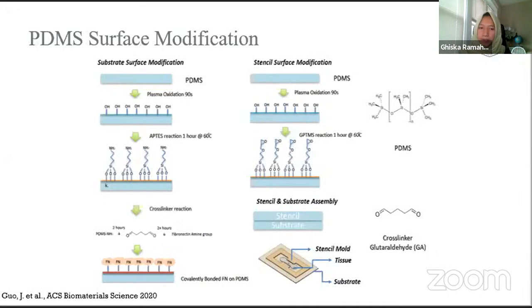And why do we use PDMS? Because with polymers, you can do some surface modification. It's pretty easy to make any modification in the atomic or molecular aspects. So here what we did is we have the PDMS, and by doing some plasma oxidation, we have this OH group on the surface of the PDMS, and this hydroxyl group would enable us to do some chemical treatment. Here we have silane treatment. So it's basically, we have this silicon oxide and a long branch of polymers, which ended by the NH2 or the amine group.